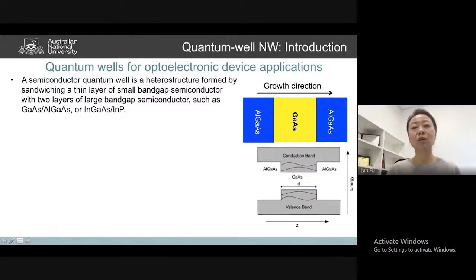In semiconductors, a quantum well is actually quite easy to achieve. It's called a heterostructure, basically a structure made from different materials. How we form that is we normally sandwich a thin layer of small bandgap semiconductor between 2 layers of large bandgap semiconductor material. Gallium arsenide is a typical III-V semiconductor with a bandgap of about 1.42 electron volts, and if you put aluminum in, you can increase the bandgap quite largely. So using epitaxial growth techniques, we can grow AlGaAs, gallium arsenide, and AlGaAs along the growth direction. You can see the energy bands of gallium arsenide and AlGaAs are different, thereby you create a bandgap discontinuity here, and then you create a potential well in the gallium arsenide layer. All the carriers like to fall into the energy levels in the gallium arsenide.